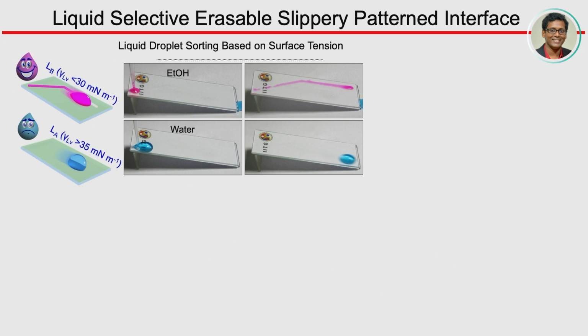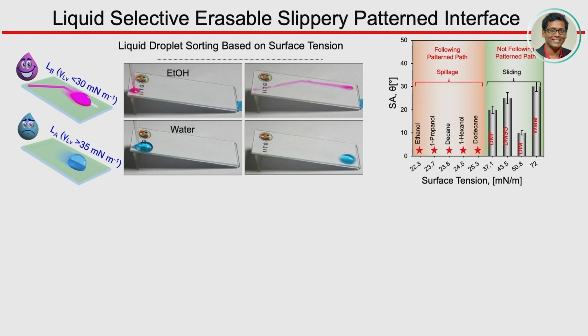What we thought is that there are many things that can be done with this. This is the kind of new avenue which has been opened up. Just to show its potential, you can think about sorting of two different liquids with these interfaces. You make a pattern and give a different path. For the low surface tension liquids, it can wet and follow this path. When you put the high surface tension liquid, it can follow the other path. That's the way two distinct liquids can be sorted out.